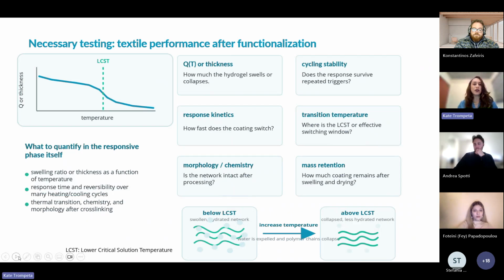I would like to close this introduction by introducing the lower critical solution temperature, which is the property that we are actually studying. What we need to quantify in the responsive phase itself: first of all, the swelling ratio or thickness as a function of temperature, the response time and reversibility over many heating-cooling cycles, the thermal transition, chemistry, and morphology after cross-linking, and all these are connected, as you may see, with different parameters. For example, the swelling ratio is a function of temperature.